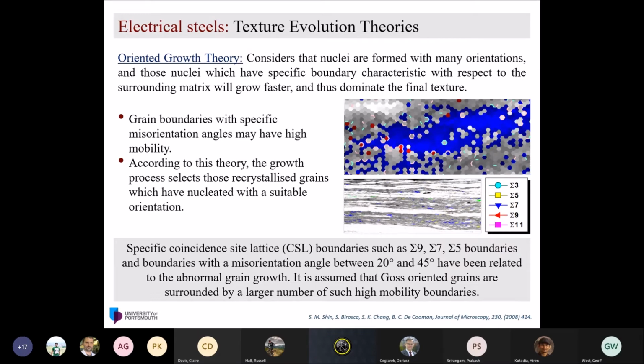These people believe these orientations already existed in the early stage of the processing, but they grow abnormally because they have a specific boundary characteristic, which is normally mainly used. Sigma 5 and sigma 7 are responsible for abnormal grain growth.